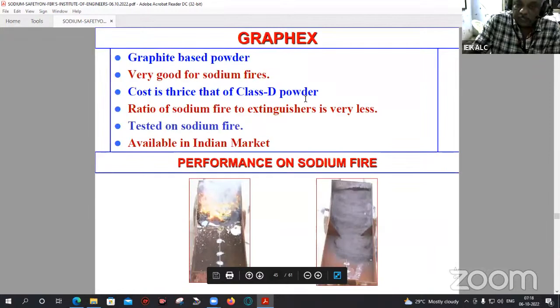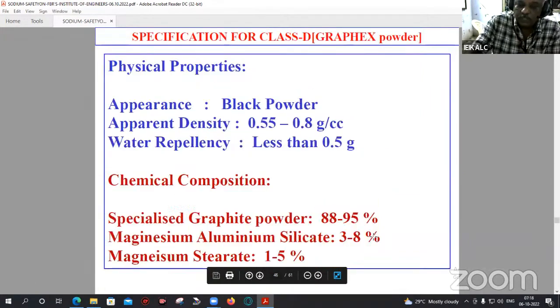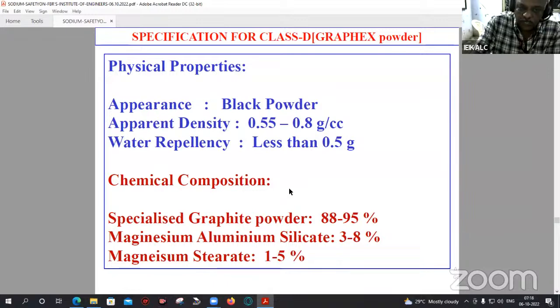And this is a graphite powder which is also available in the market, and it was also quite good. It has been tested. You can see a fire created and the extinguishing also, you can see here. In the specialized graphite powder, around 88 to 95% is graphite powder. Aluminum silicate is 3 to 8%. Magnesium stearate is the third one. Magnesium stearate is added in all the powders to prevent moisture ingress into the powder.